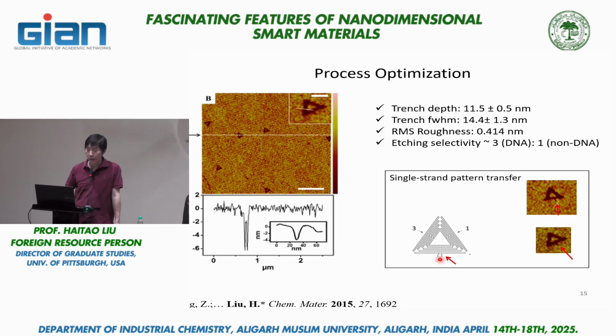That's by design. And what we find is, in at least some of the etched structures, we find this small tail in the transferred pattern, indicating that even a single-stranded DNA is capable of delivering this catalytic effect to the substrate, and you can essentially carve the shape of a single-strand DNA into a silicon oxide substrate.